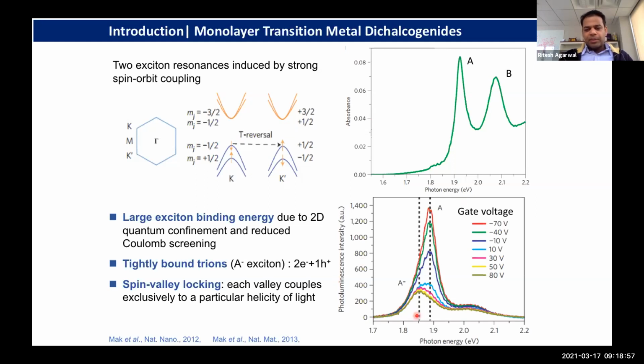So this is an important aspect, and for this talk, another aspect is because the carriers are not adequately screened, there is long-range, many-body interaction, which can occur over length scales many orders of magnitude more than any other semiconducting material which is not a monolayer. Again, because of inadequate screening. And if you inject any carrier or extract any carrier from the system, one can change the physics, or the dynamics of the exciton recombination, and people have also shown the formation of trions even at room temperature or close to room temperature.